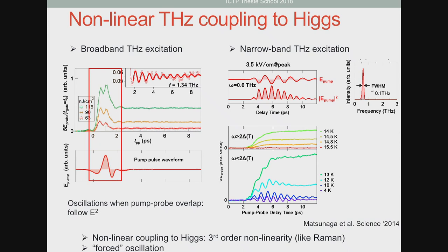And what you can see is that the probe seems to follow not the electric field of the pump, but the square of it. If you look, this minima here corresponds to this maxima here. This maxima corresponds to this maxima. So it looks like when both pump and probe overlap, there is a signal in the probe that is following E square. You can see that more nicely if, instead of using a single cycle terahertz waveform, you shine a multi-cycle waveform. So you use, for example, a narrow bandpass filter. You narrow down in frequency your pulse. Of course, you broaden it in the time domain, and this time you have many oscillations. And if you do that, you see really clearly these oscillations in the probe signal, and they are nicely following the square of the pump.